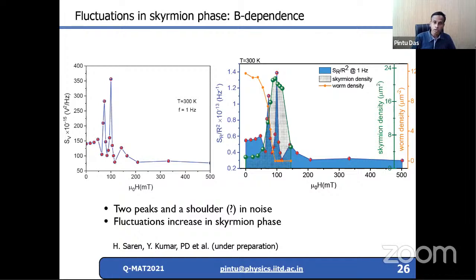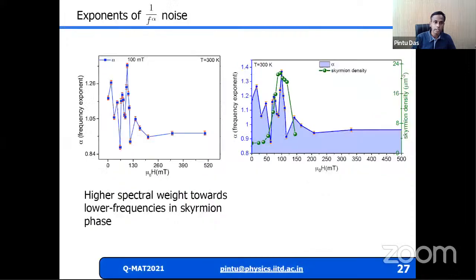Now, to look at this in more detail, we have plotted the frequency exponent as a function of field. What we see is that as the field progresses, the frequency exponent goes down, less than 1. So 1 is perfectly 1 over f. Less than 1 would mean that the dynamics is faster. And then as the skyrmion phase is fully developed, on the right side, the frequency exponent goes past 1.3. So it is about 1.35, 1.4.